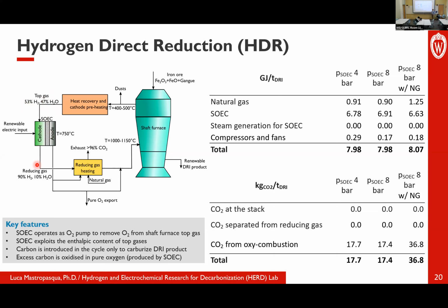That hydrogen-rich stream can be sent back to the DRI furnace after some waste heat recovery and preheating as a reducing gas. So this gas here at the inlet of the furnace will be a hydrogen-rich gas that is produced using water splitting, using electrolysis. And of course, if you use wind or PV resources to power the electrolyzer, that becomes a renewable hydrogen.